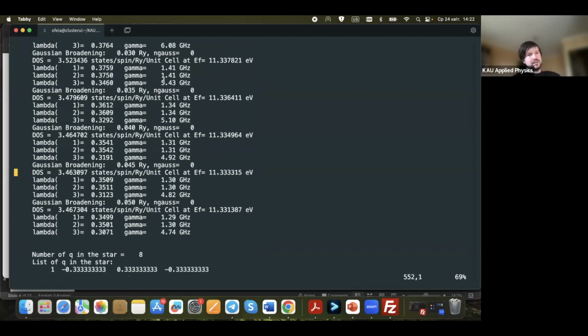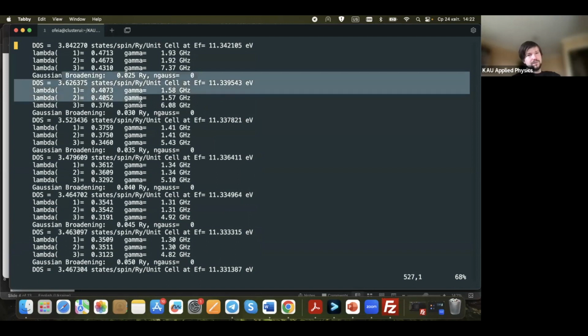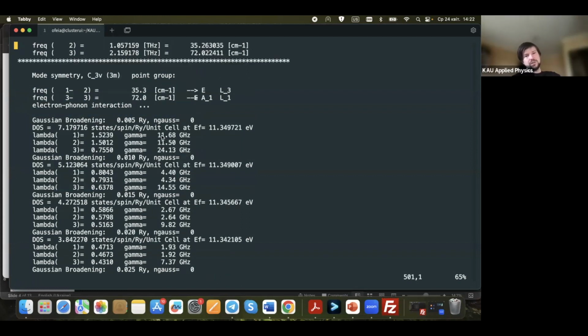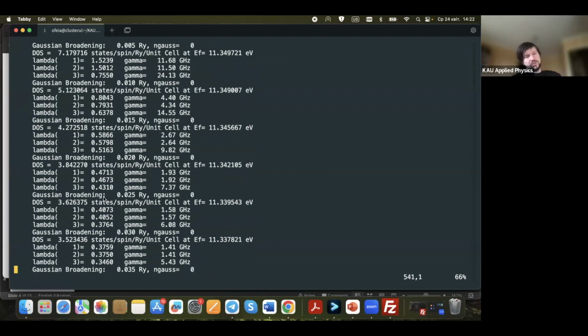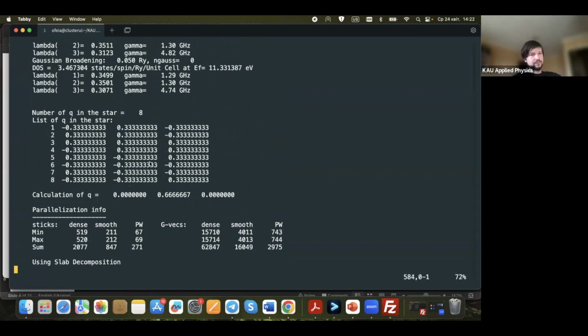I think it's maybe this 5th point here. 158 and 141, the difference is not so huge. But here the differences are huge, from 11 to 4, from 4 to 2, and so on. So maybe from the 5th step of this broadening, we get some reasonable results.